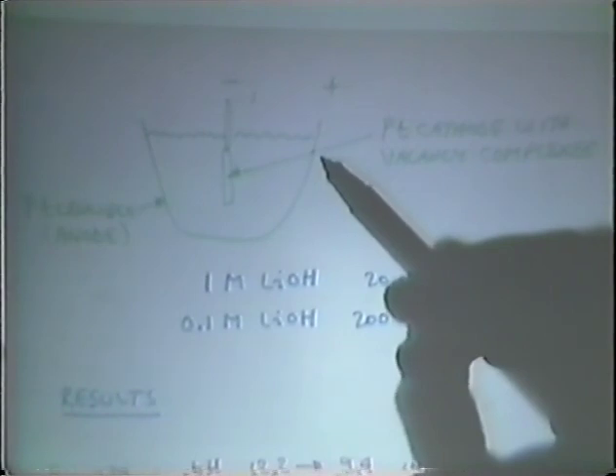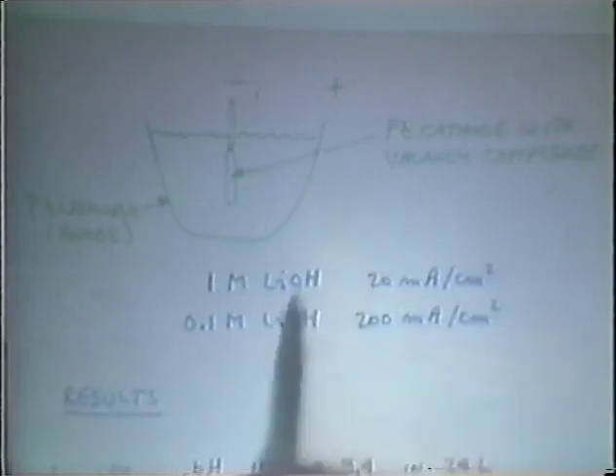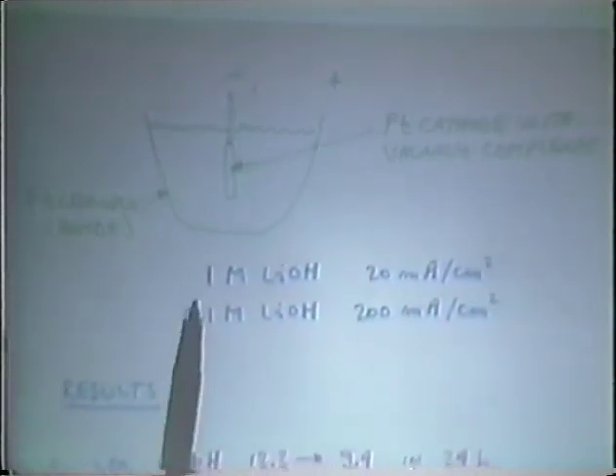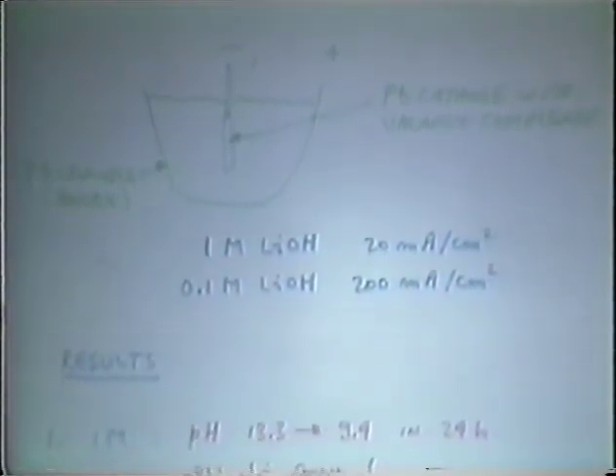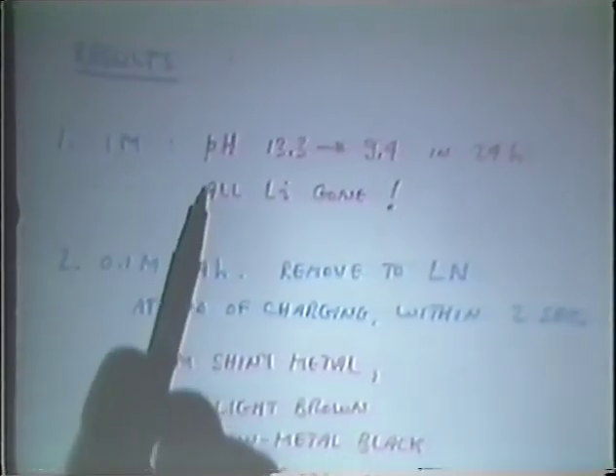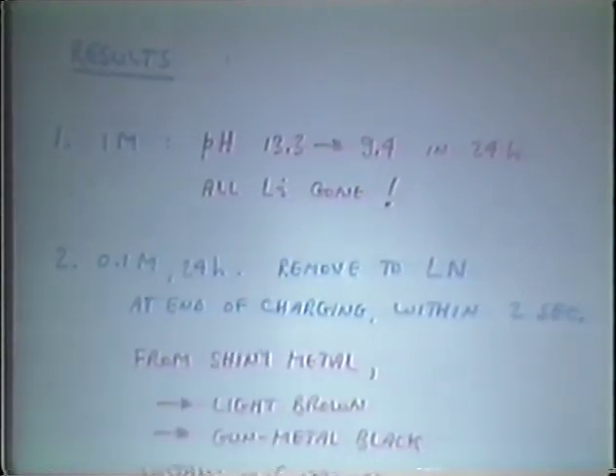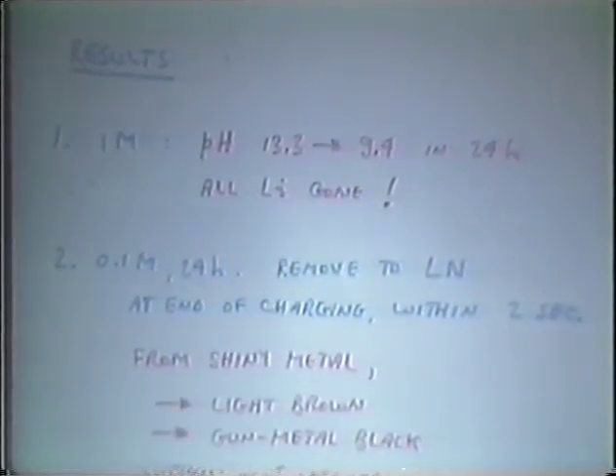The cell we used had a platinum crucible to avoid any problems from dissolving stuff into the electrolyte, and a platinum cathode. We've used both a 1 molar and 0.1 molar lithium hydroxide solution at different current densities. For the 1 molar solution, we observed the pH to decrease from 13 something down to 9 something after 24 hours of electrolysis. In other words, all the lithium was gone from the electrolyte.